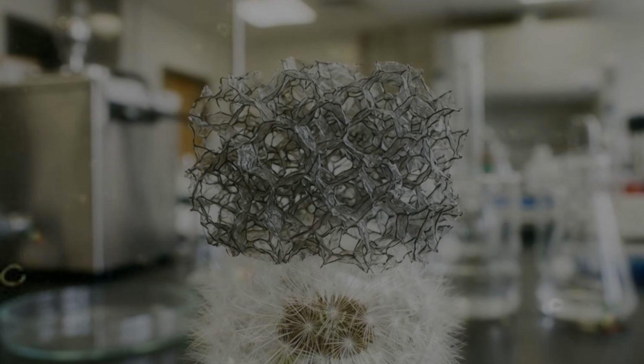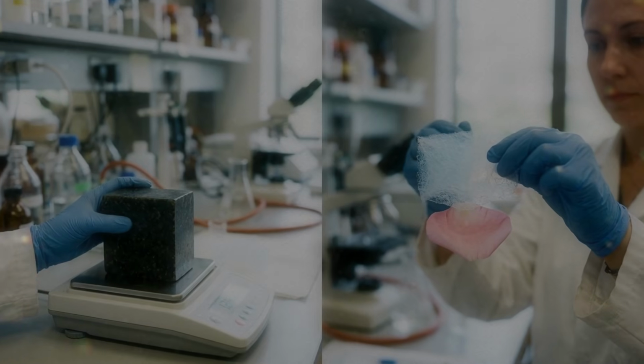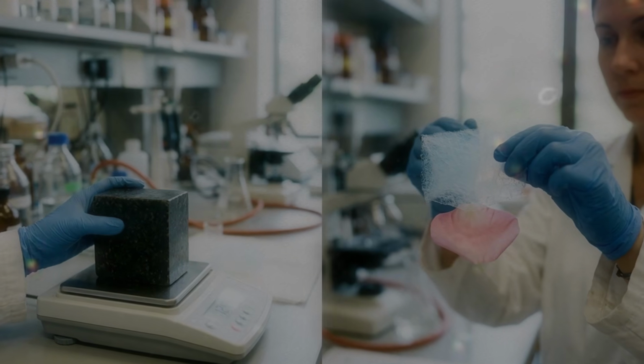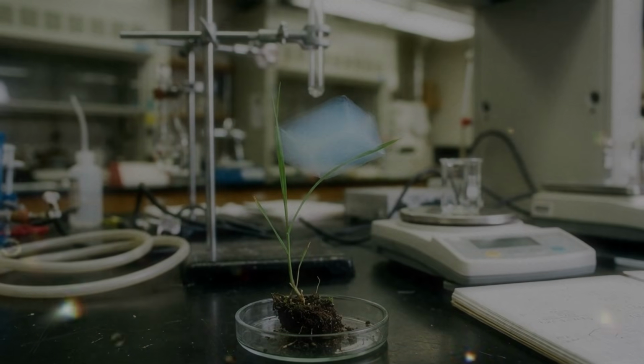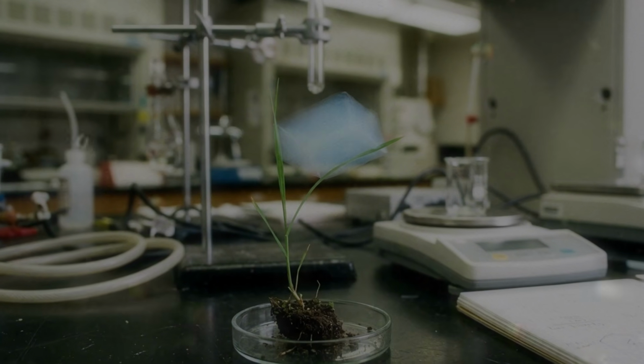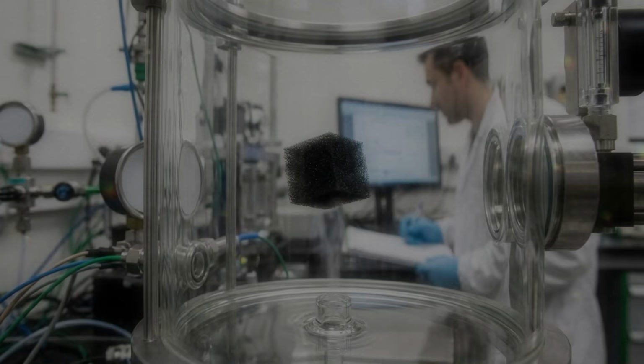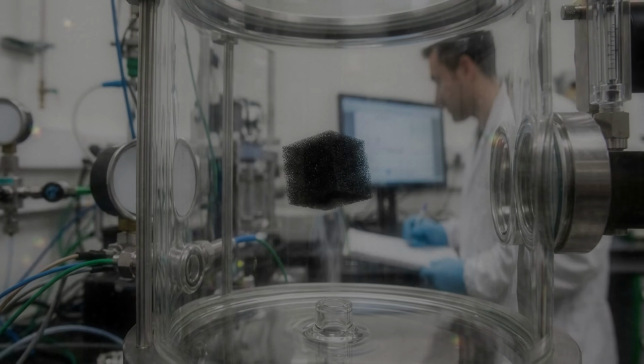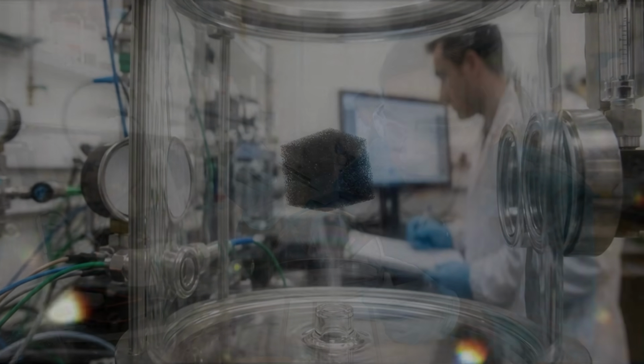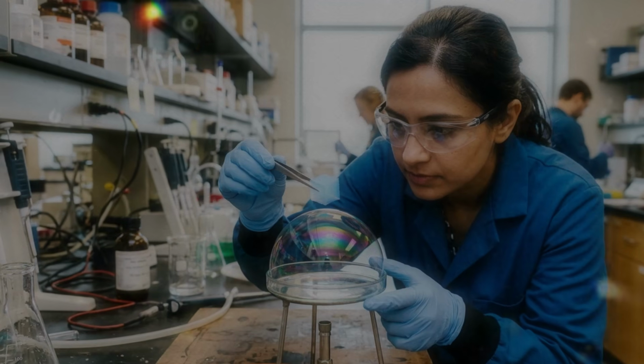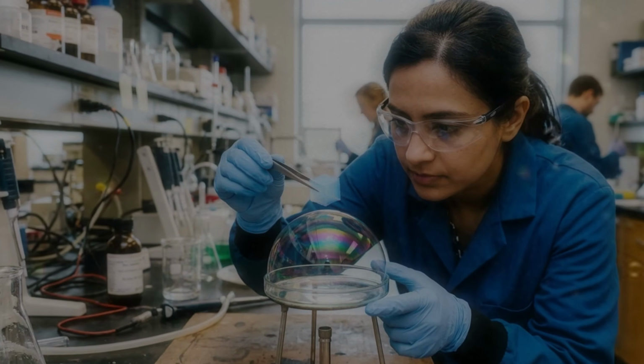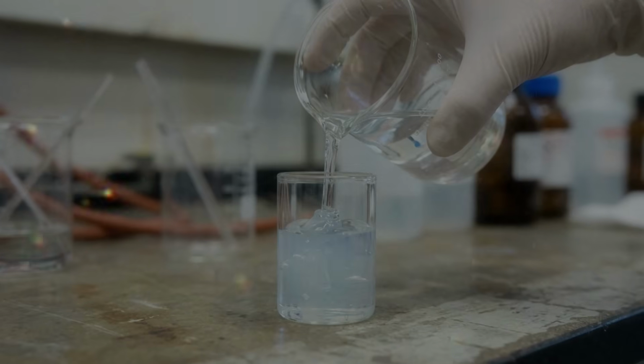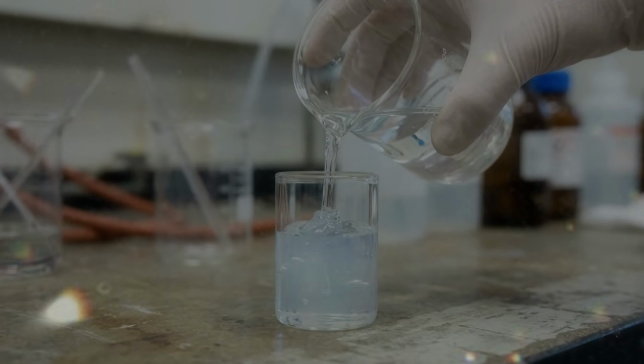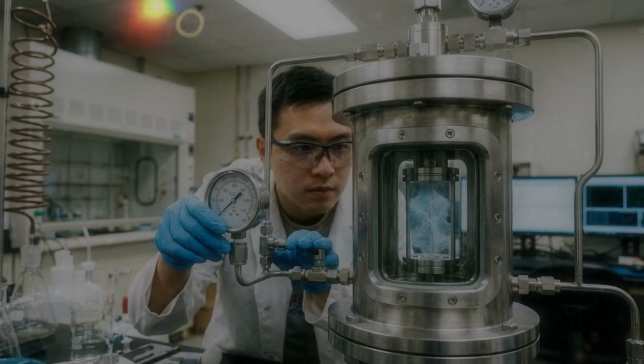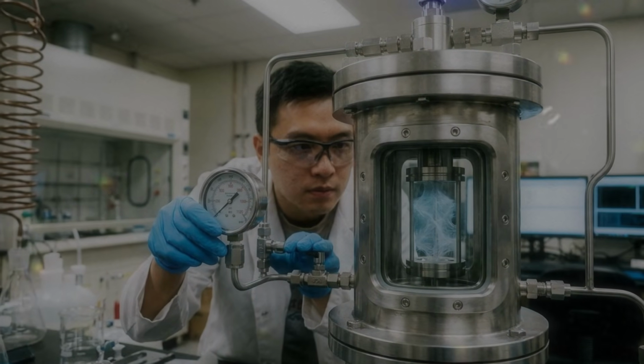Air passes through the structure and fills its spaces. Only the fine carbon skeleton displaces a meaningful amount of surrounding air. Since that skeleton occupies a very small fraction of the total visible volume, the buoyant force is not enough to lift the whole object in the simple way suggested by its bulk density. A sample can still appear to float in photographs. It may rest on a flower, a blade of grass, a piece of cotton, or the fine hairs of a plant. It may cling to paper through static electricity. A faint air current may move it. These demonstrations reveal how little the sample weighs, but they do not show ordinary free flight.